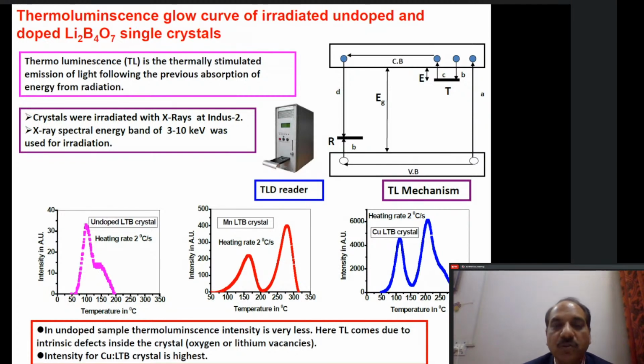And this material is used for personal dosimetry. So whosoever is going in the radiation environment will wear a badge which we call a TLD badge, thermoluminescent device, and that device will record the amount of radiation which that radiation worker has received, and after that, the badge is read through a thermoluminescent dosimeter, and we record these glow curves. The area under the curve will tell you the amount of radiation that particular worker has received, because every radiation worker is monitored very closely, because there is an annual dose limit to which a radiation worker can be subjected.